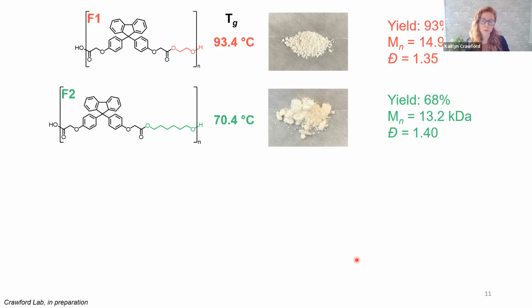And we can begin to control the glass transition temperature further by controlling the flexibility of the backbone polymer chain. So you see this 70 degrees is much lower because this larger number of carbons allows for greater flexibility, which means that less energy in the form of heat is required in order for the chain to become flexible, which is the Tg that comes as an output of that, versus the shorter carbon chain that restricts flexibility. So you have a higher glass transition temperature.